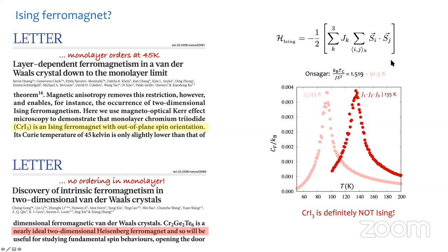We calculated all these things and then did a Monte Carlo simulation, and we find that if we take J1, J2, J3, then the Tc is of the order of 140 Kelvin, which is much higher than the experimental Tc. I'll show you that there is a dependence on the on-site Coulomb interaction, but these results are done with a very small U. So further increasing U will increase your Tc further.